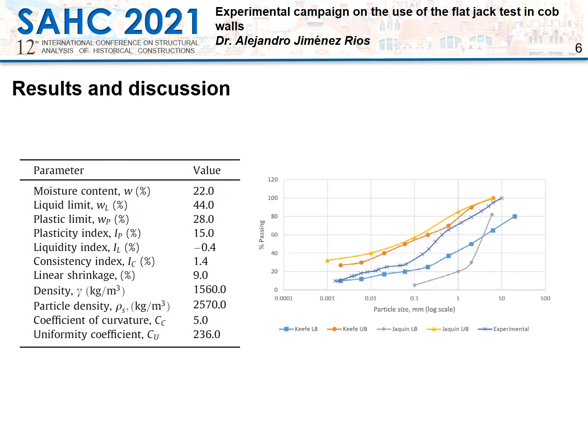In this figure, it can be seen that the particle size distribution of the soil perfectly fits within the upper and lower bounds recommended by the reference authors for the construction of cob walls, which represent the necessary amount of clay content in order to achieve the bonding of bigger particles and provide the cob wall with cohesion.